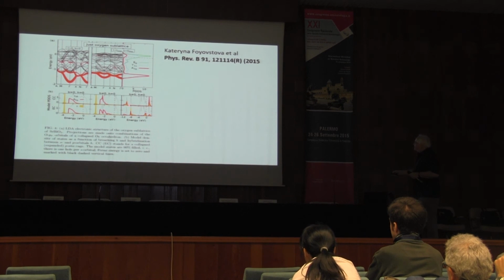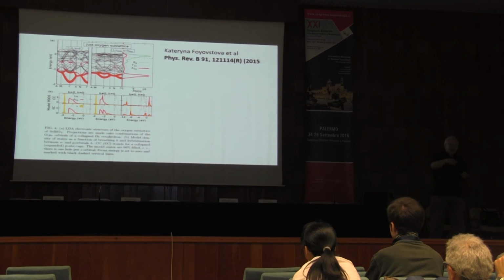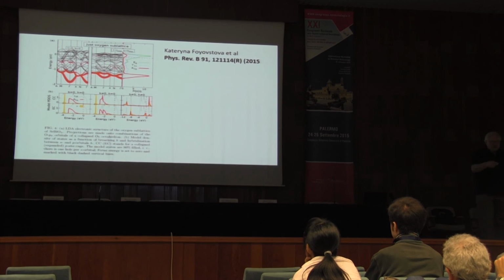And then, when you switch on the hybridization, this is still the zero hybridization with the bismuth states down here. If you switch on the hybridization with the bismuth, the bismuth states move way down in energy, down to 10 electron volts here, and we were up at 4 electron volts here. An oxygen A1G symmetry state gets pushed out over here. This is a molecular orbital of an octahedron of oxygens with sigma bonding oxygen p orbitals.